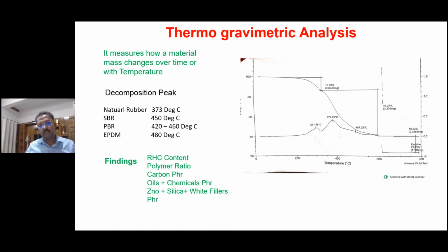From the residue, we can estimate by gravimetric analysis zinc oxide, stearic acid, silica, and other white fillers. So almost 99% of the composition we can identify from TGA and FTIR.